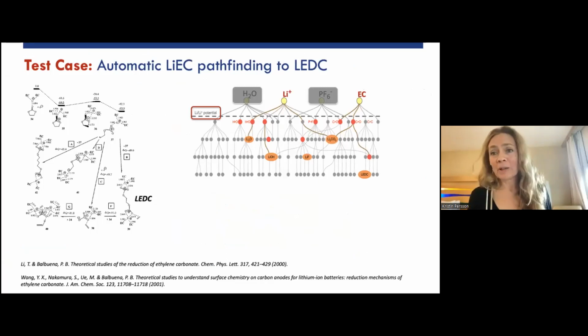Okay, so the first thing you do when you have a new methodology is, of course, you test it on existing knowledge, right? And we're very grateful for the work that's been done by other modelers, such as Perla Balbuena, who about two decades ago carefully laid out the different mechanistic decomposition paths of lithium-coordinated ethylene carbonate, which allows us to test our methodology. So we take a very simple system, lithium and EC, exposed to lithium metal potential. And we break every possible unique bond in EC under different coordination scenarios. We add as many electrons as the system wants to take up, and we form these fragments, and we start recombining them completely automatically without any manual intervention. And then we see where the system leads us.